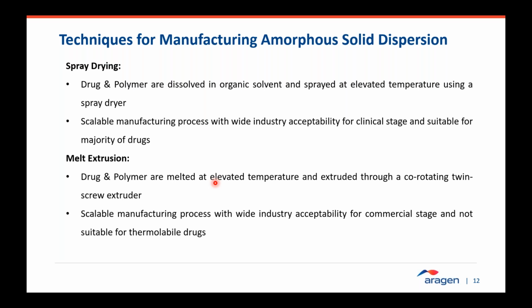The next two slides illustrate the typical techniques or processes used for manufacturing amorphous solid dispersions, both at mini scale and at a commercial stage. The first and most commonly used process, widely applicable to most compounds, is the spray drying process, where the drug and polymer are dissolved in an organic solvent or a combination of organic solvents and sprayed at high temperatures using a spray drying machine. This is a scalable manufacturing process. If the drug has appropriate solubility in a suitable and safer organic solvent at a reasonable solids content of 5 to 10%, it is a perfect process to manufacture for clinical and then commercial stage.